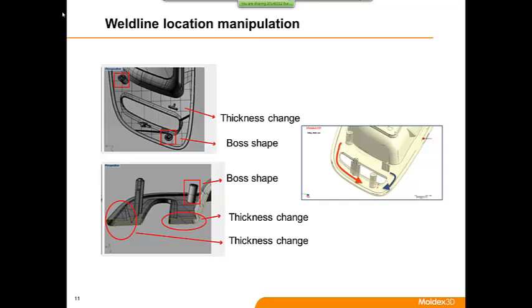So this is another example, because sometimes in the real case the mold has been fixed, the part design has been fixed. There's limited room, you cannot change too much on the gate location. So what can you do? We can still make a lot of adjustment just based on some tiny features or not so important features in the part. For example, for this handle lead, it's the back side of the part that we are doing a lot of changing, either on the boss shape or on the thickness.